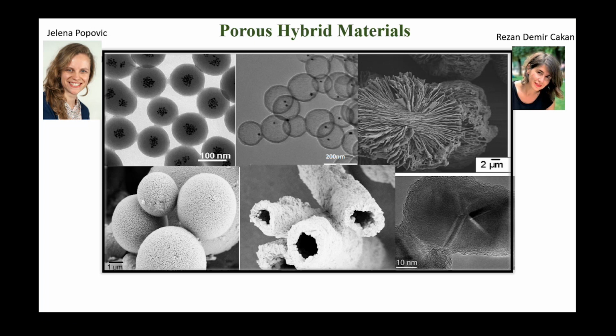And you could see how you can nicely load platinum nanoparticles supported on carbon in just one step. You take a platinum precursor, glucose, do hydrothermal carbonization, and platinum will be reduced in situ and deposited on these carbon materials. Now, if you want to play really at the more nanoscale with these materials, you can put one single nanoparticle in the middle of a carbon hollow sphere by using latex nanoparticles on which you deposit one platinum nanoparticle, and it's a bit tricky to do that, and then you coat it with carbon, and when you remove the latex, you form a hollow sphere with one platinum nanoparticle.